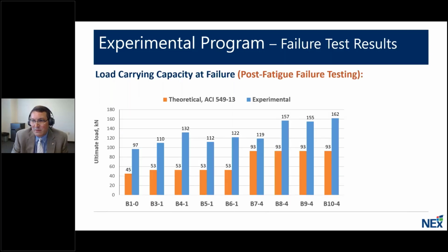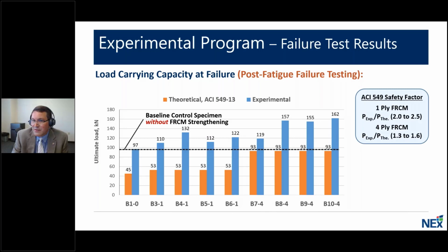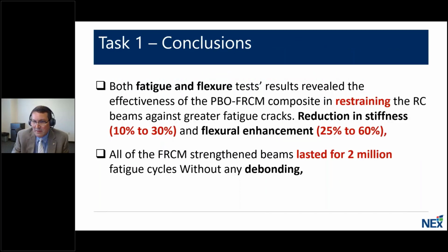Comparing the experimental results of testing capacity at failure to theoretical values using ACI 549, we see that the factor of safety was over 100% as shown here for 1-ply and over 30% for 4-plies. Again, for 4-plies, we have that premature debonding failure as the governing capacity as the strain level and the reinforcing level is higher. So for task 1 conclusions, we see that fatigue and flexure tests revealed the effectiveness of the